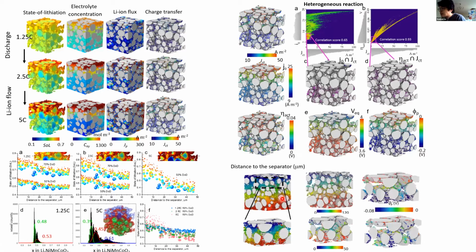Here, the pore phase is color-coded to show the travel distance from the top at the entrance of the electrode to the bottom. You see it's farther away, so this is red. Even in this small area, at the same height, you see this is larger, or more red, meaning it's a longer travel distance compared to here. This is because of the local difference of the tortuosity or because of the morphology of the pore.